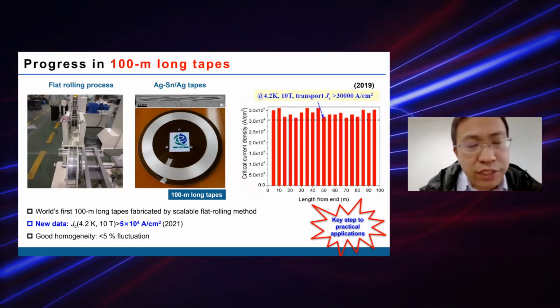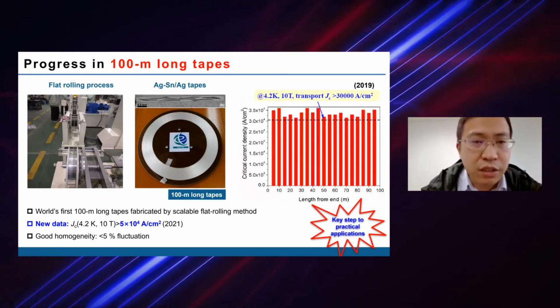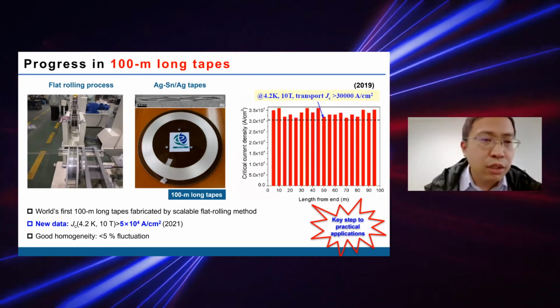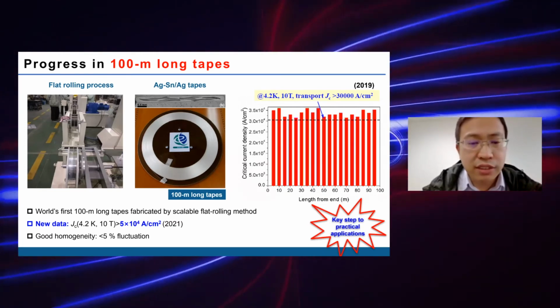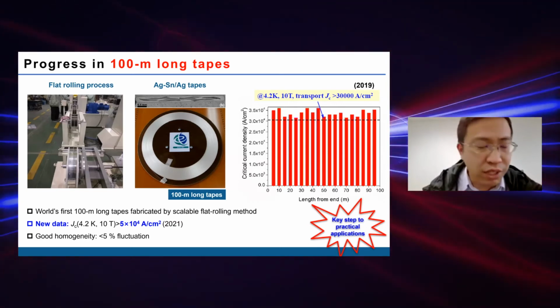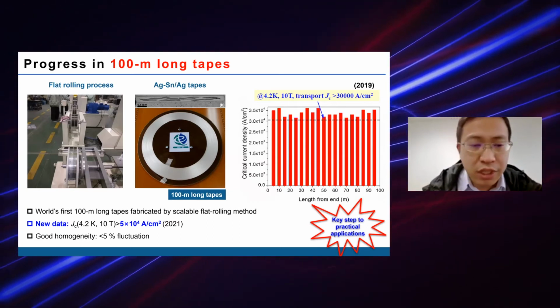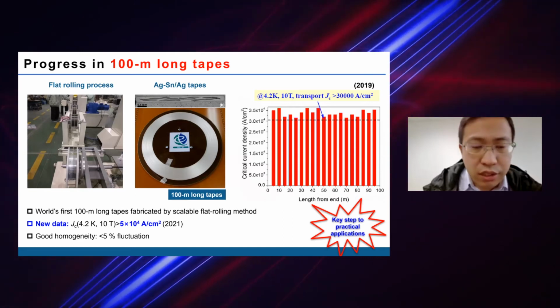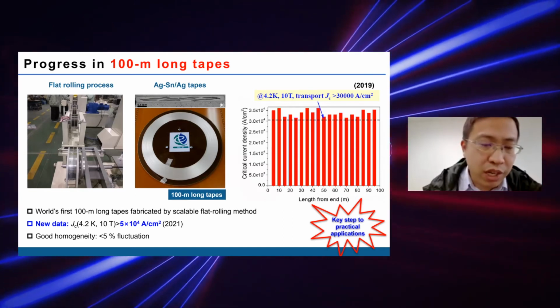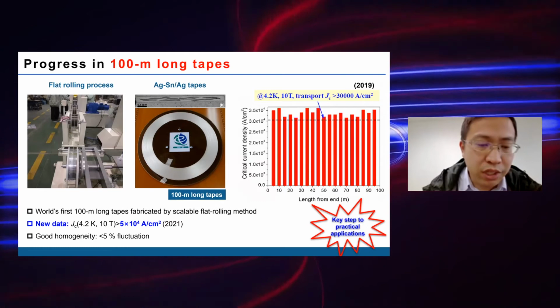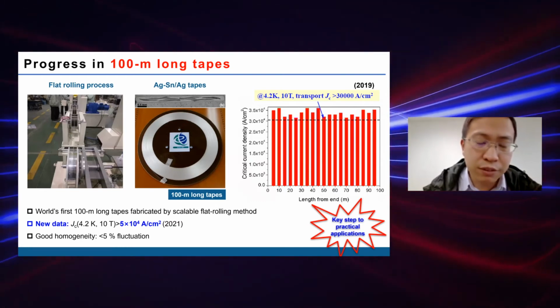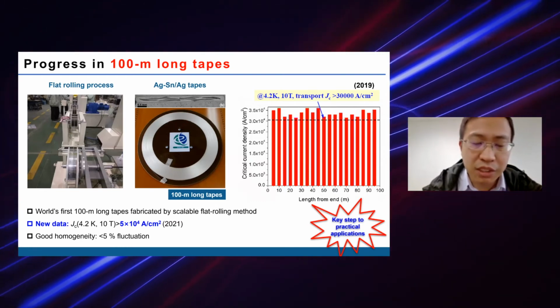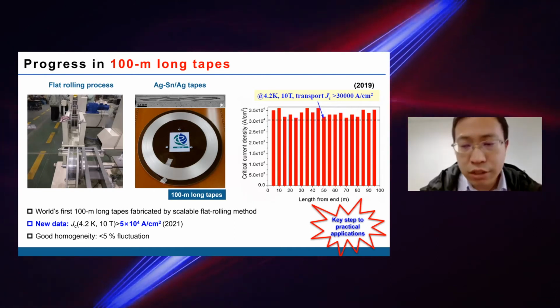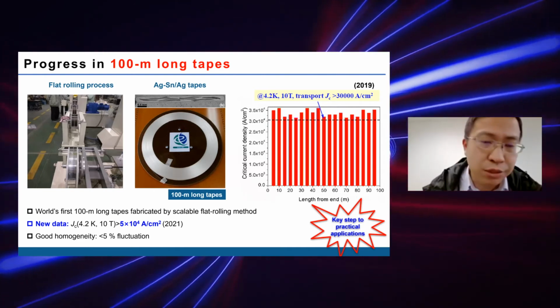And of course, we are continuously fabricating 100 meter long tapes by using the flat rolling process. And the tapes have a very good homogeneity. Our new data shows that the critical current density at 4.2 Kelvin and 10 Tesla is above 50,000 ampere per centimeter square. And this is a very important step to practical applications.